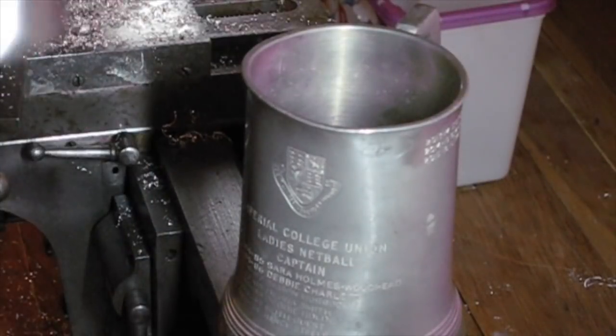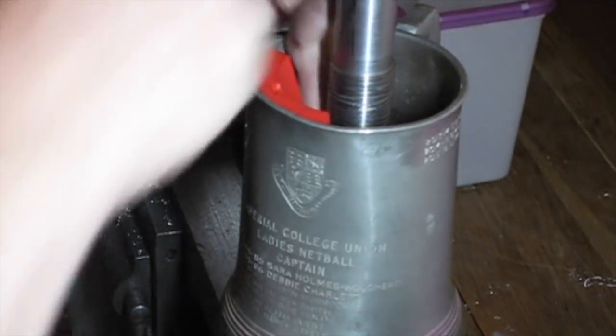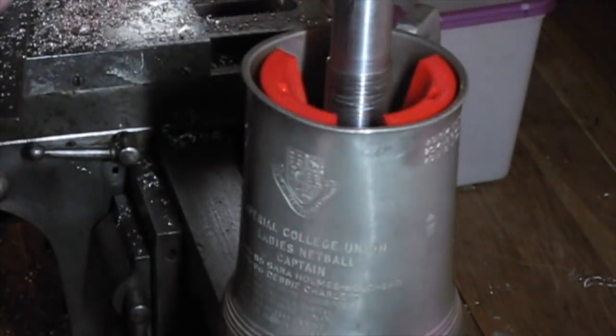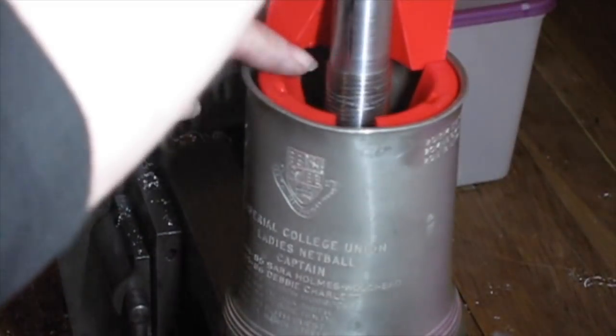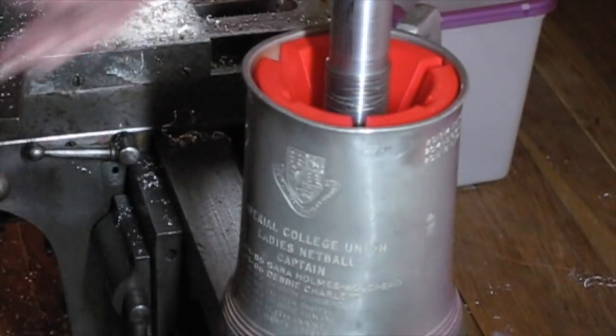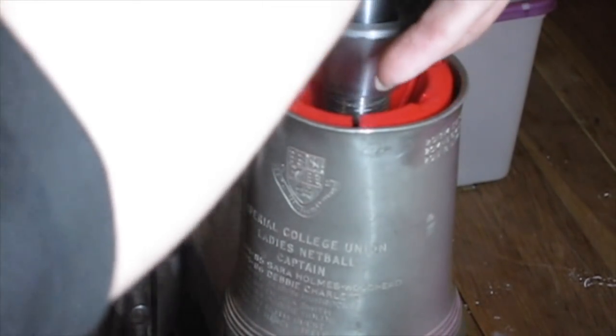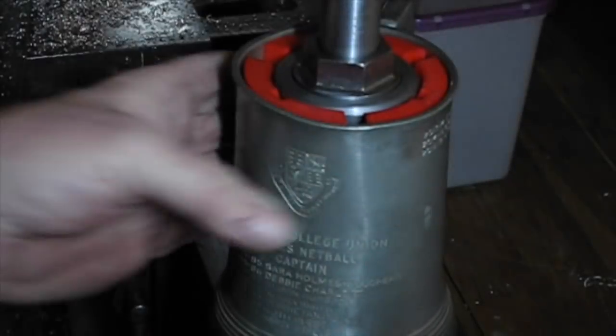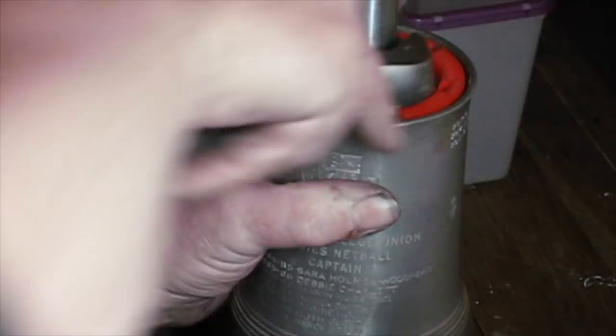To hold the pots for machining, I made an expanding mandrel specifically for the job. There's an inner steel part with a cone at the end, some 3D printed wedges, and the whole thing is expanded by a second cone with a keyway, and then clamped down by a large nut. This allows me to machine the bases out. I was told by a pewterer that this couldn't possibly be done because the handle whirls around. I can only assume he had too small a lathe, because it's actually not a problem apart from one of balance.